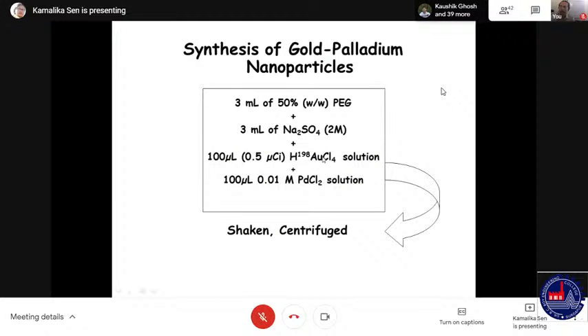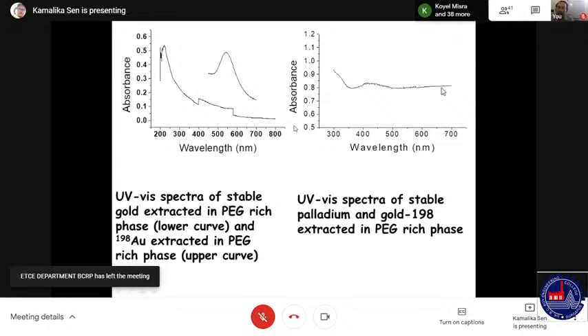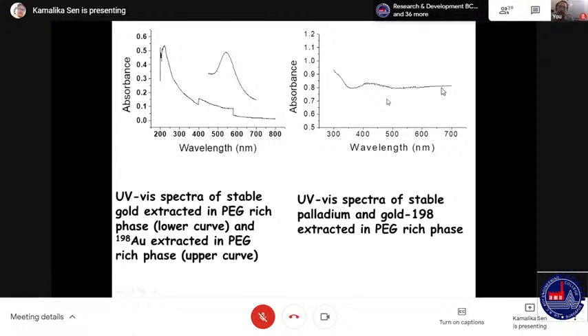Similarly, just like the previous set, we added palladium chloride solution to it and did a similar experiment. After decaying for 25 days, we found that the absorption spectrum shows no peak in the visible region. This is actually the characteristic property of a palladium-containing solution, which does not show any surface plasmon resonance in the visible range of the UV spectrum. This agrees with several previous palladium nanoparticle reports, and matched with our observation.